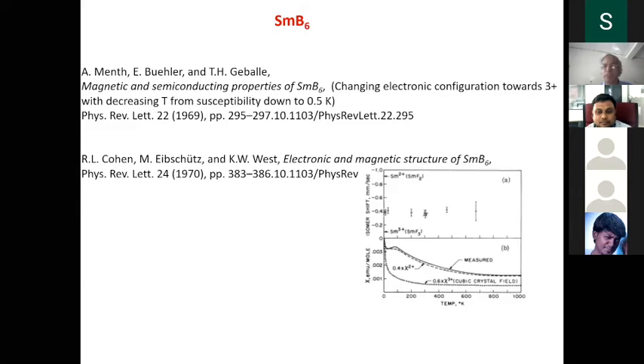Basically, susceptibility is intermediate. Okay, on top of it, one of the valence states should be magnetic. Samarium 3+ should be magnetic, whereas samarium 2+ is a non-magnetic, which is not magnetic. This should be magnetic, whereas they found the material is not magnetic. Suppose the f electron has lost its magnetism, despite the fact that in this temperature range you see curious behavior, but there is no magnetism. You follow what I mean?